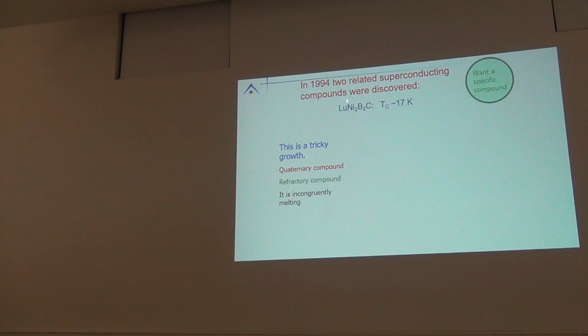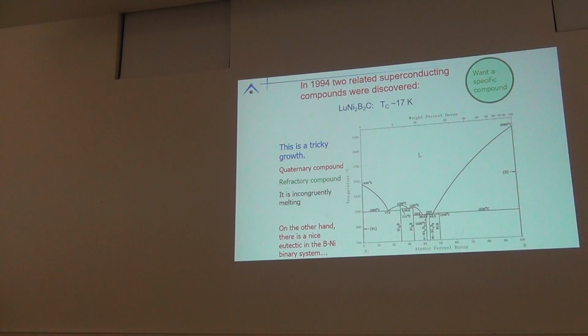It's a tricky growth. Quaternary, as we saw yesterday, a quaternary phase diagram is no fun. Refractory, boron and carbon are incredibly high melters. Lutetium and nickel aren't that low. And it's incongruently melting. All right? Now, at the time, solution growth had been done. I'd been doing it, decanting at 700. For those of you who do solution growth, when I started doing this, decanting at 400 C was considered hot. I pushed it to 700, 800. This is when I pushed it to decanting at 1200. Okay, that's